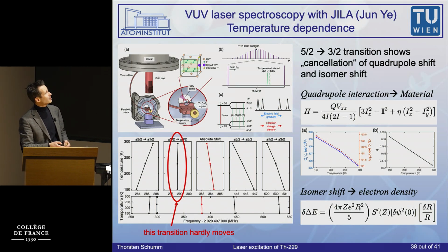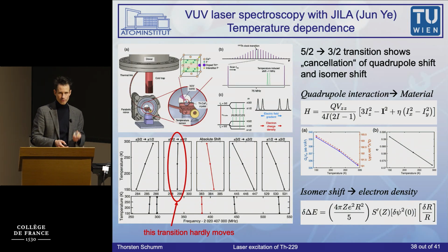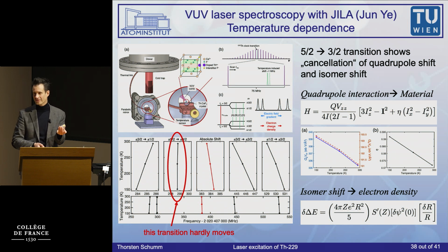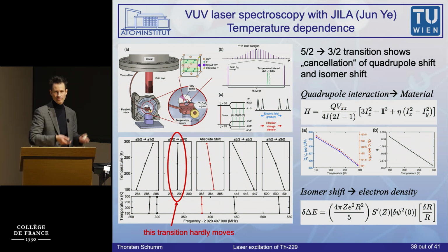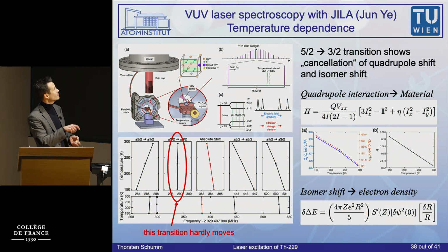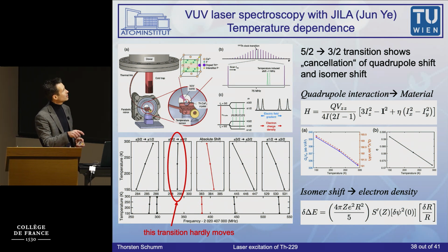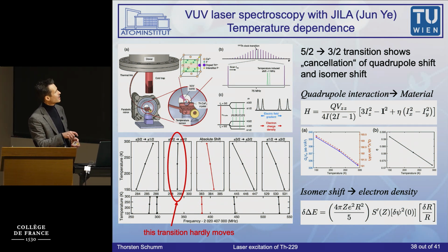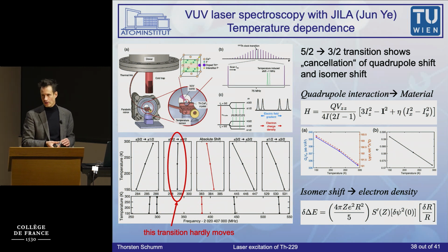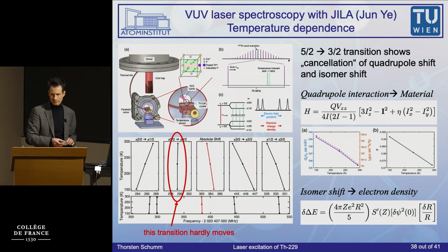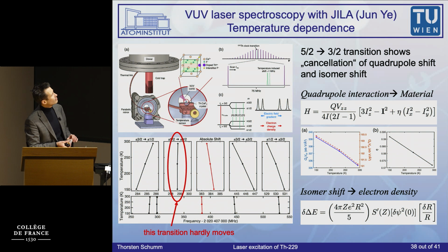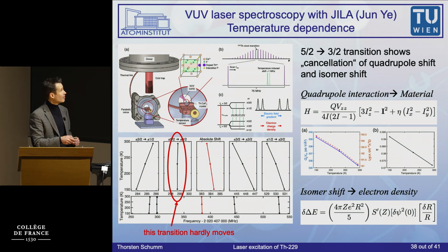So we looked at these lines as a function of temperature. The good thing about this is it's very easy to change the temperature. Just put a Peltier or just some cryogenic cooling. So we changed that over a range of 100 Kelvin. And we looked at how these lines move. This is in megahertz, okay? You see for about a 100 Kelvin change, the transition lines move on the order of 2 megahertz. There is one that hardly moves at all, which is quite interesting for clock operation.